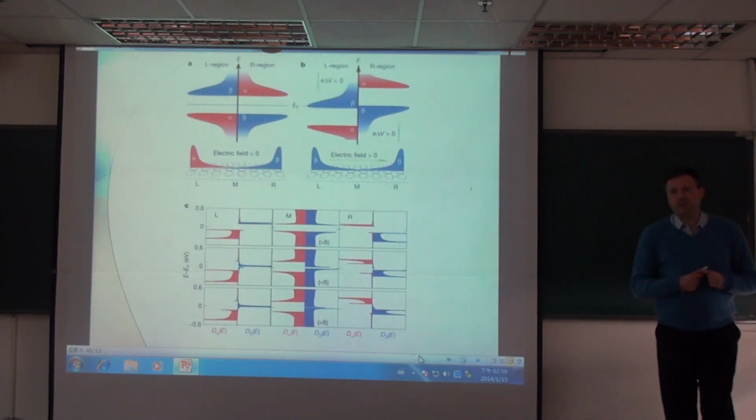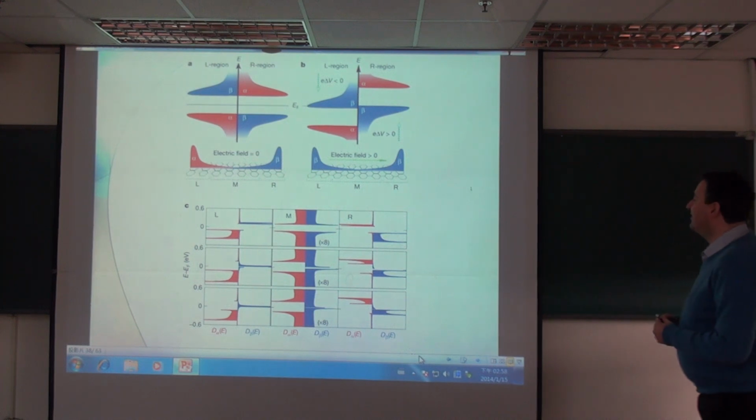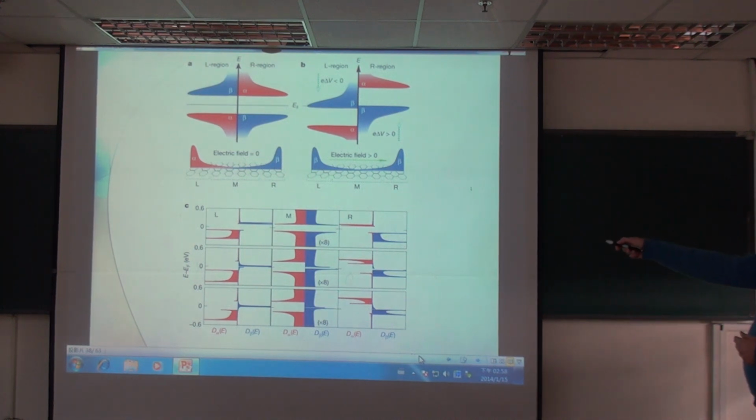What you observe according to unrestricted DFT calculation is the following. This is what we get as zero field. Thus we have a symmetry breaking in spin densities. There's localization of spin alpha on one side and of spin beta on the other side of the zigzag graphene nanoribbon. And because they are localized in different regions of space, when you apply an external field, they experience different effects. Electrons belonging to the spin alpha system are stabilized. Electrons belonging to the beta spin system are destabilized.